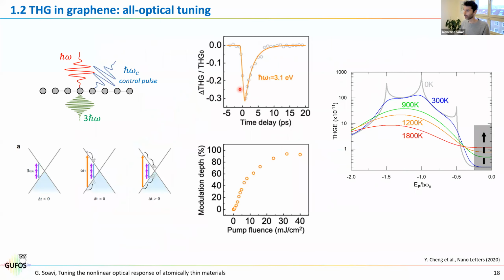Okay, so now let me take one step forward, because this suggests that all-optical modulation of third harmonic generation is possible. And we could do it basically with the mechanisms that I was showing before. So basically, we have our h bar omega, we generate a 3 h bar omega, and then we add another pulse that we call the control pulse. And with this pulse, we will be increasing the electronic temperature, and by doing that, we will change the efficiency. And this could be a way of achieving all-optical modulation of third harmonic generation.